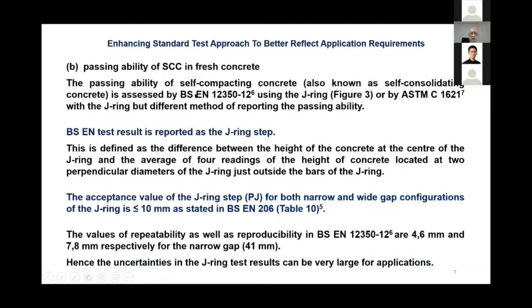Now, the passing ability of self-compacting concrete, in the US they like to call it self-consolidating concrete, using the J-ring. Both in ASTM and EN, we use the same ring, but we don't treat the result the same way. In the EN standard, we call it the J-ring step. That means the change in height between the one in the middle and the concrete that has flowed past the ring. This is the J-ring, and you're supposed to be less than 10 mm.